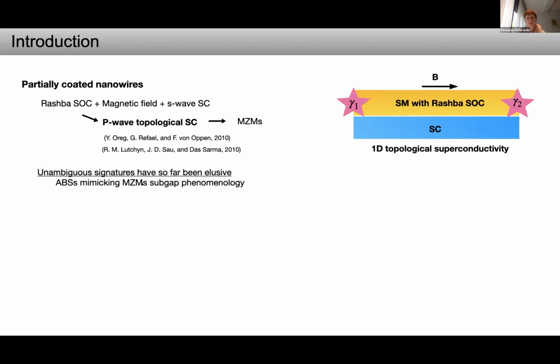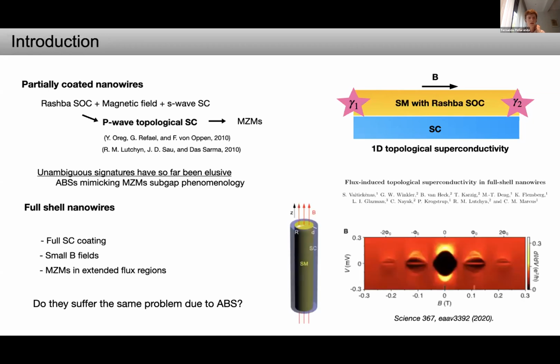However, unambiguous signatures of these topological non-trivial states have so far been elusive due to the fact that Andreev bound states may mimic all the subgap phenomenology in tunneling conductance associated to Majorana modes. So a recent proposal by S. Vaitiekėnas and collaborators, named full-shell nanowires, also predicts the existence of Majorana modes in extended flux regions in integer lobes. The difference between these nanowires is that now the superconducting shell fully coats the semiconducting nanowires, and there is no longer a requirement for high magnetic fields, which places them as a promising platform to finally observe them.